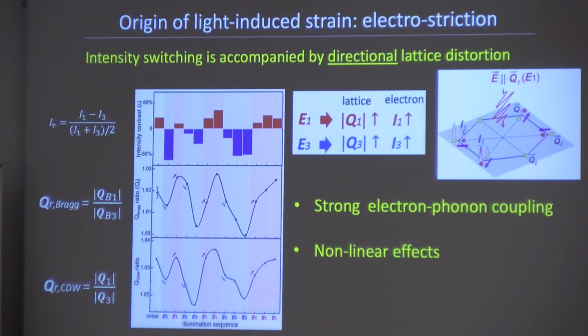So now we have, and again, this is fully repeatable, a sequence of light pulses. Every time the intensity in one direction gets higher, like this red is higher, there's a distortion. So let's see, this blue is higher. Lattice distortion has gone up in that direction. Then red, it goes up in that direction. So the lattice follows this charge density wave.